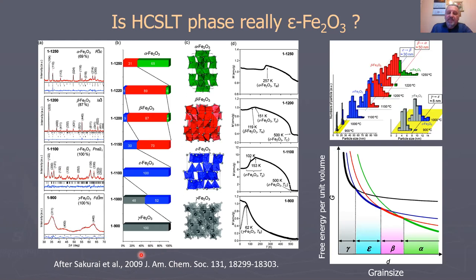And in this very carefully orchestrated synthesis, Sakurai and others have shown that one can obtain four polymorphic forms of iron 3 oxide depending on the calcination temperature, which is shown here with numbers. Another important takeaway from this study is that epsilon iron oxide has a very narrow stability field in terms of grain size.